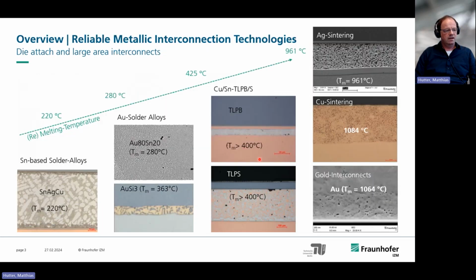I would like to talk today about some of the very important metallic interconnection technologies. So most important is, of course, the tin silver copper soldering, or some other slightly modified alloys, which are used for die attach and also for large interconnects. Of course, what is also very much in use today is the silver sintering. Copper sintering is coming up a little bit now, and we are investigating this also as a future technology. We will see if it replaces the silver sintering somehow. Of course, we could also use gold or the gold-rich solders, but these are more used for applications where costs don't play such a big role.